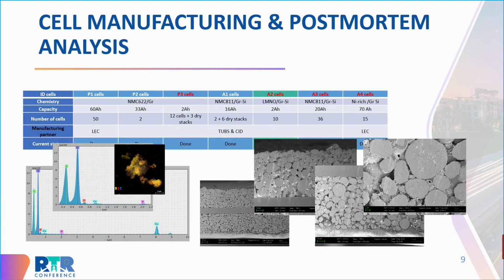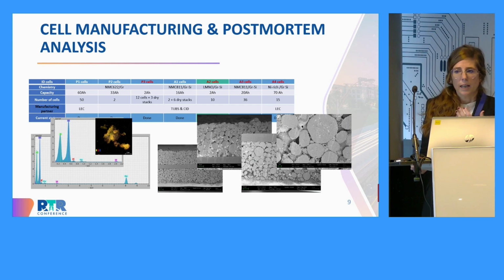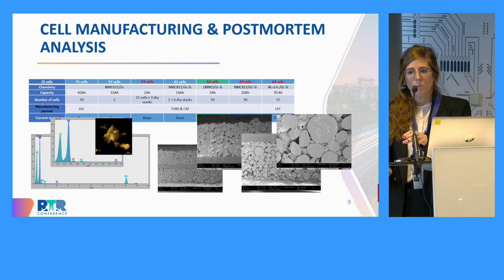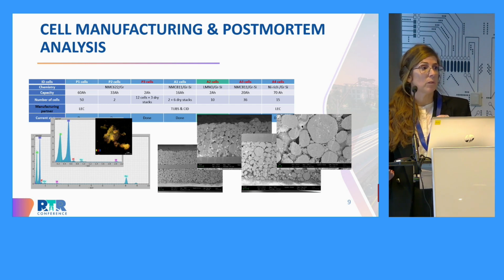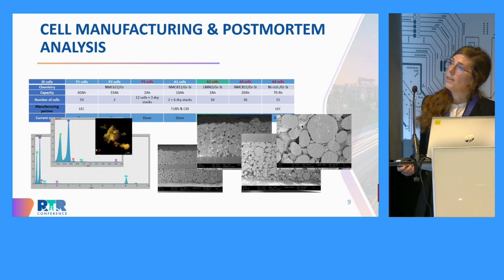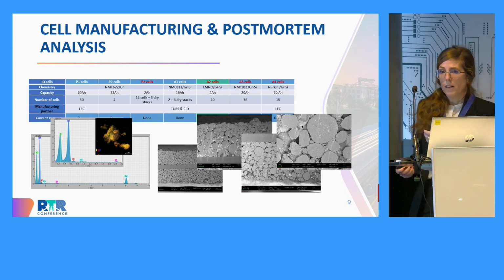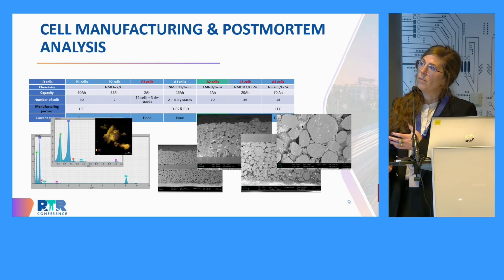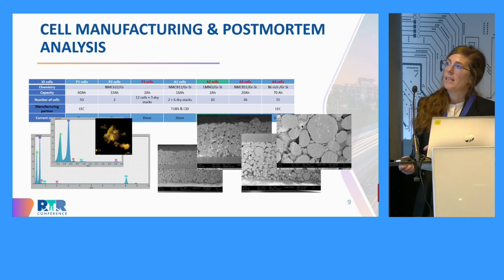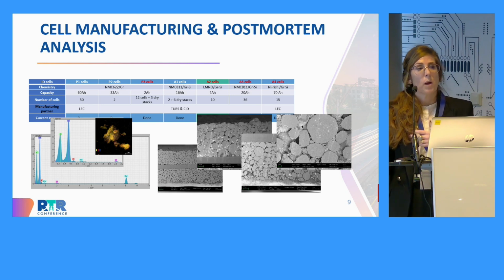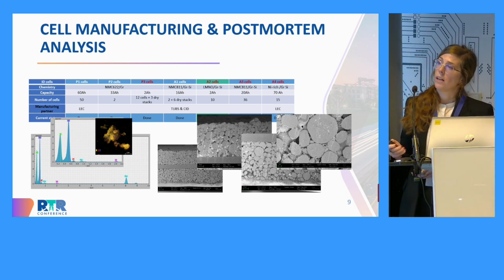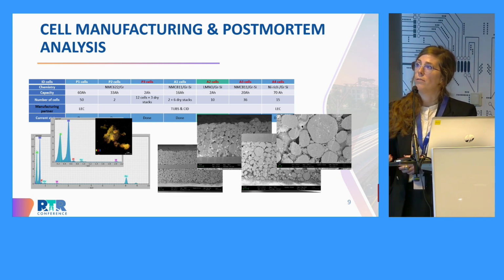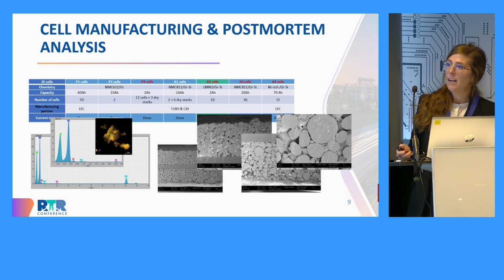And again, it's available. So regarding manufacturing, these are all the cells that were manufactured. And we aged them, so we properly made a design of experiments, in a way that we were identifying specific degradation modes for each of the experiments, and we carried out cycling as well as calendar ageing. And then we did postmortem. So we were able to identify the degradation modes, and this is really relevant for model validation. And together with the cycling data, through the QDB analysis, we were able to quantify lithium cyclable loss or active material loss, and we used the data for model validation.